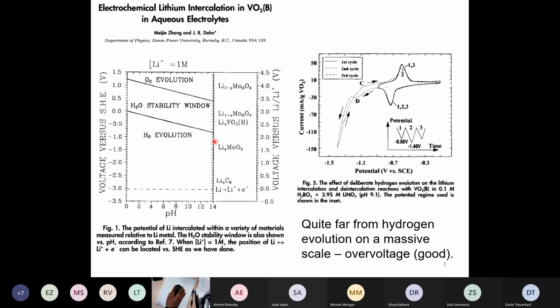Well, one of the things you have to verify is that you're far away from these side reactions that you don't want. So for example, hydrogen evolution. What happened here was we were doing cyclic voltammetry, and Meiji Zhang just ran the voltage down lower to see where hydrogen evolution would begin.